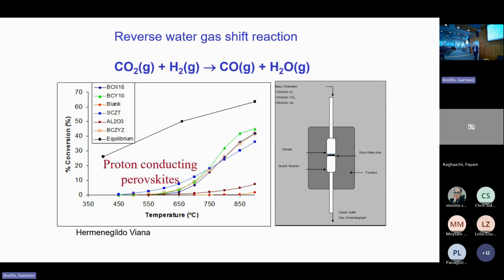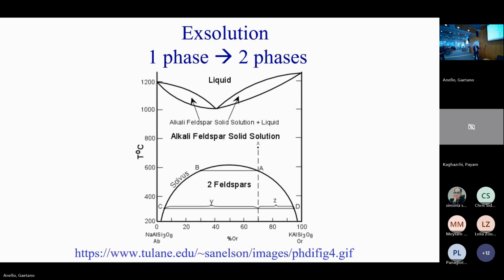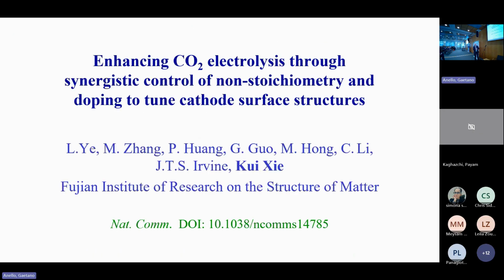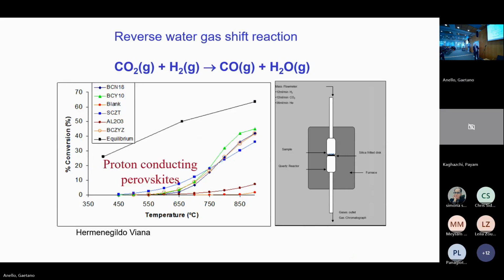Now, looking back at some of our previous work on proton conductors, we were trying to determine the stability of these materials in CO2 under reducing conditions, because we know that barium material is not stable under CO2. We did some TGA, and weirdly, we found lots of carbon monoxide, as we have here. So you've got high conversion by the water gas shift just over the proton conductor. So the electrolyte is itself a catalyst, and that's why it affects the conversion.